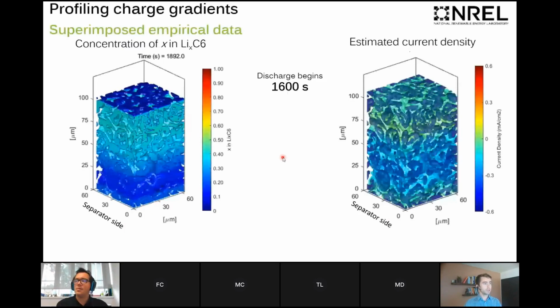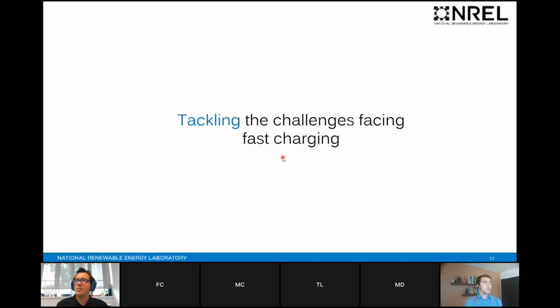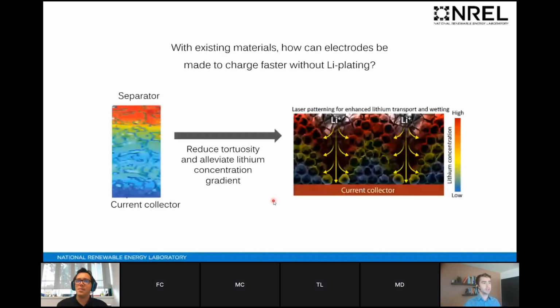Now, we don't want to actually change the materials in the batteries, because performance is key. We need to maintain high energy density and long life. So the current electrolytes and electrode materials are very good at that. We want to look at how we can continue to use existing materials with electrodes, but make the electrodes charge faster without lithium plating. And one way to do that is to reduce the tortuosity and lessen the lithium concentration gradient. So we'd like to go from this, where we've got a severe lithiation gradient, red close to the separator, blue close to the current collector, to a less severe lithiation gradient inside the electrode.